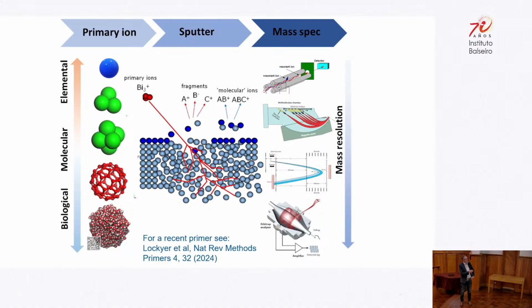And we can use a probe beam, either single atoms. The single atoms like this we would use in semiconductor applications, where we want to get the ultimate spatial depth resolution of a device. So every semiconductor company around the world, every semiconductor fabrication plant, has a SIMS instrument, and they will use this, and they can get a depth resolution of less than 1 nanometer per decade change of intensity, and from that they'll work out what boron dopant distributions are and things like that. It's a very important technique in the semiconductor world.